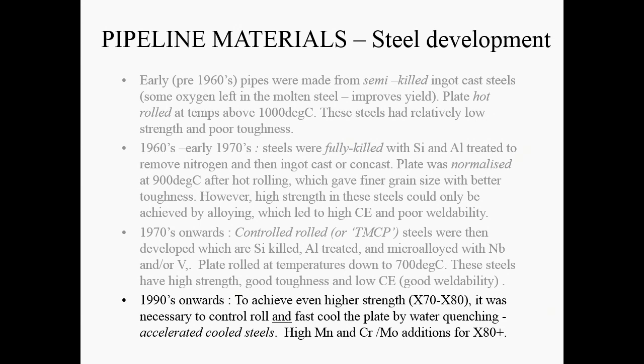So we try to avoid that process by cooling as fast as possible to keep the small grains that we've just spent a lot of money making. And when we go above X80, we also have to add a bit more manganese to the steel, and chromium and molybdenum, because we want to get the possibility of carbides forming in the system, and that will give you the higher strength, but then you've got to ask questions about carbon equivalent and weldability for these higher grades. So X80 I've always regarded as the tipping point. Up to X80 you can improve things by all these other processes and maintain the weldability. If you go much above X80, then the steels are inherently less weldable, but you may need to use that for other reasons in your applications.